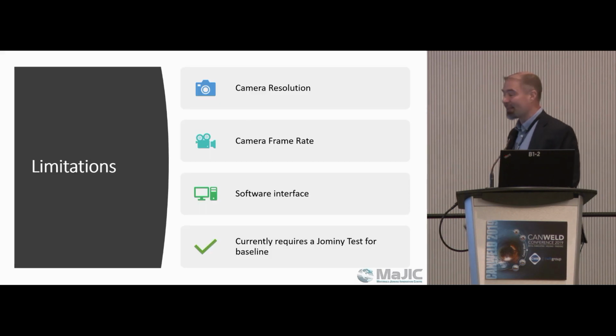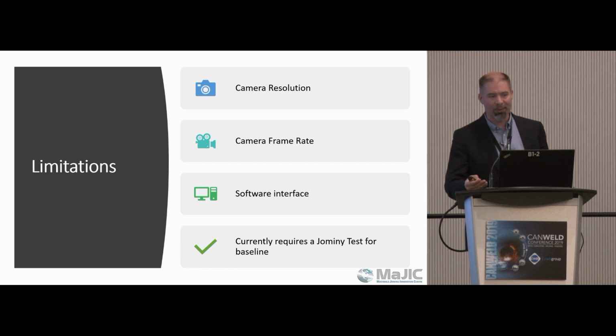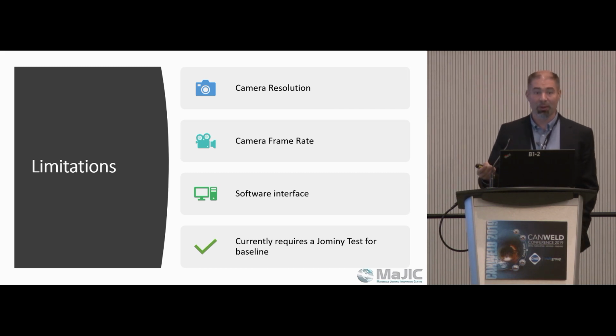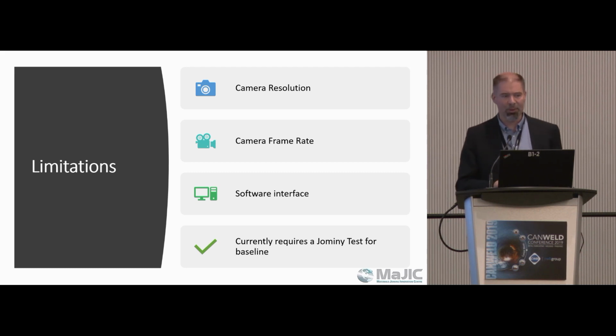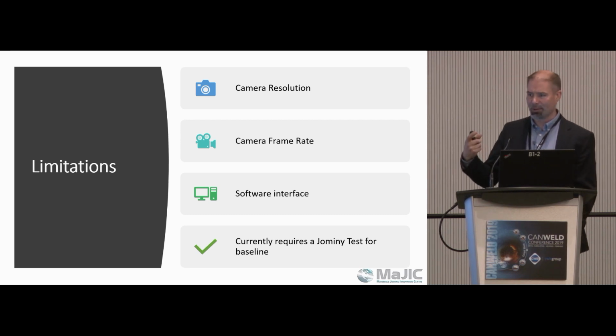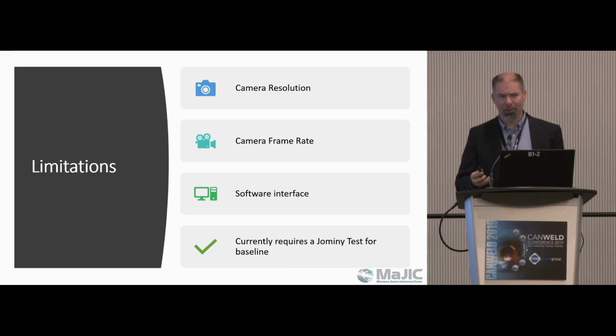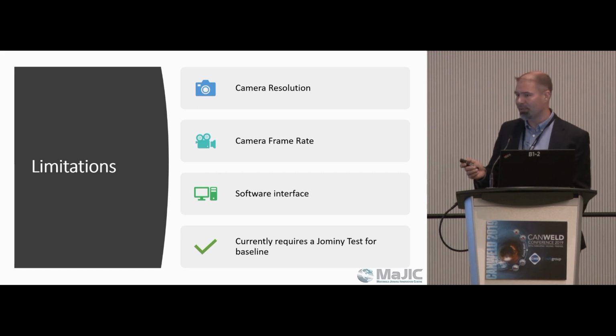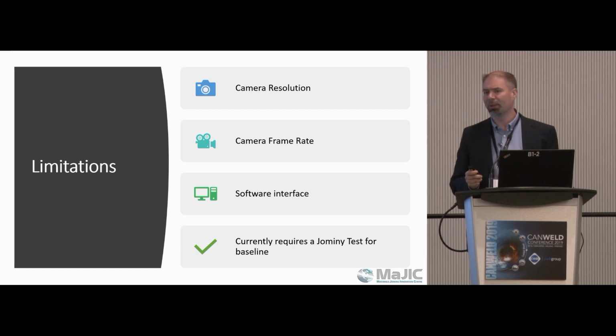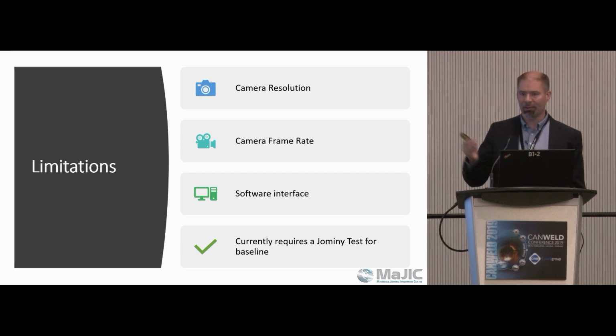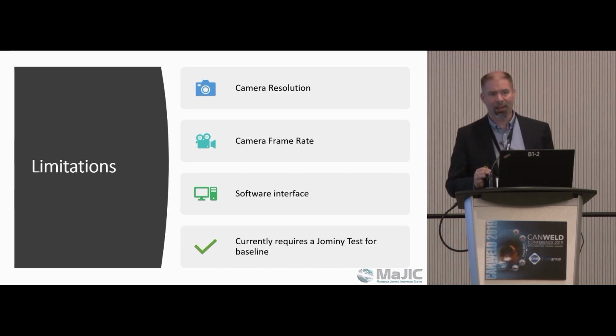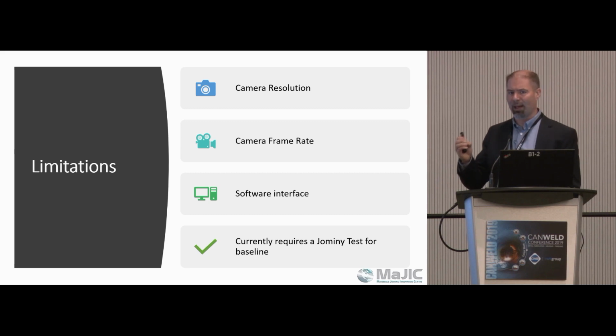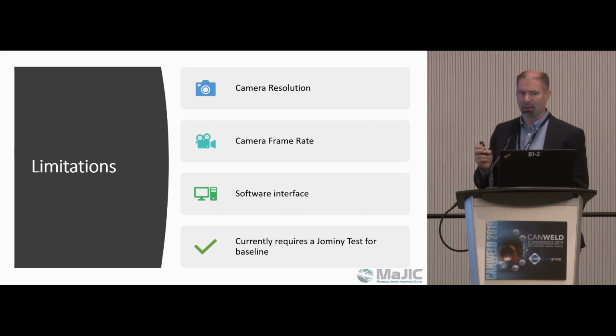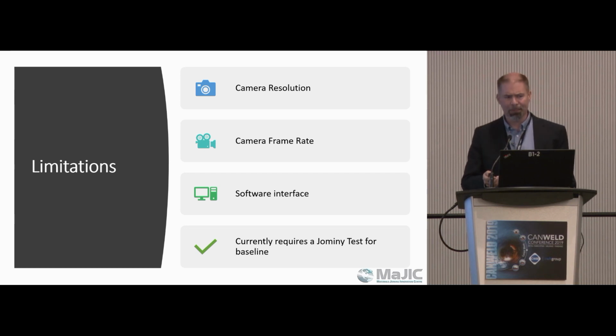So some of our limitations, as I mentioned, we do have some limitations with this process. The camera resolution is one of the primary ones. So it is a fairly high resolution camera, but high resolution for a thermal camera isn't the same as your high resolution on your phone. We're a 640 by 480 resolution, so you got to get pretty close. The camera frame rate, we're able to record video at 30 frames per second. When you're dealing with cooling rates that are very fast, that has some limitations. We can't exactly capture every fine detail in the milliseconds after the weld passes.